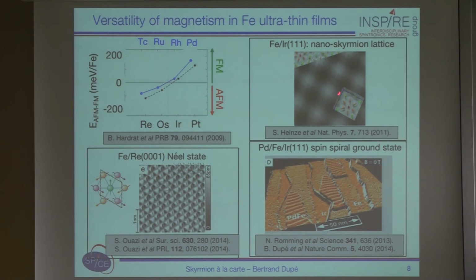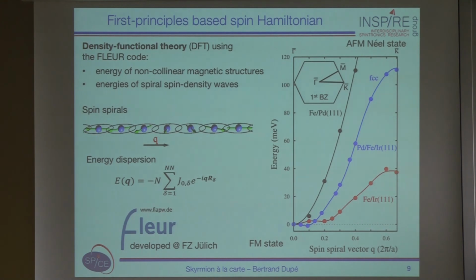So how we understand this change is by calculating what we call the dispersion curve. We use the code called FLEUR. It's a DFT code with a full-potential linearized augmented plane wave basis set. This code is very nice because you can calculate non-collinear magnetic textures, and you can also calculate what are called spin spiral density waves.